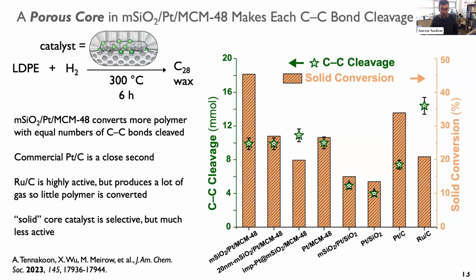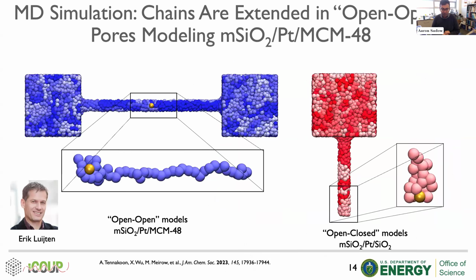into longer, rather specific lengths. So more of the cleavages go selectively to making the products we want, whereas a catalyst like ruthenium on carbon makes a lot of methane, which we don't want, and that's reflected in the high activity for cleavage, but the low activity for polymer conversion. And I think overall, this is a really powerful principle for thinking about how you're going to get selectivity and how you're going to get to relatively specific products that we can design.